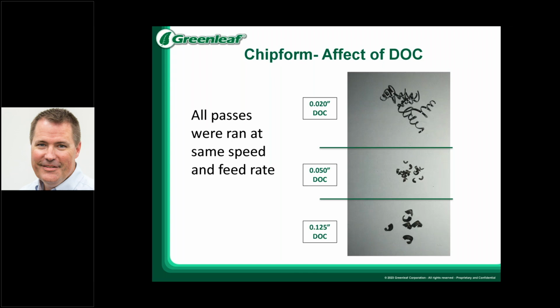The images with the 50 thousandths depth and the 125 thousandths depth, which both fall within the ideal range recommended for the chip form, have much shorter chips. You're able to control those and have those evacuated with coolant and standard operating procedures for the machine.